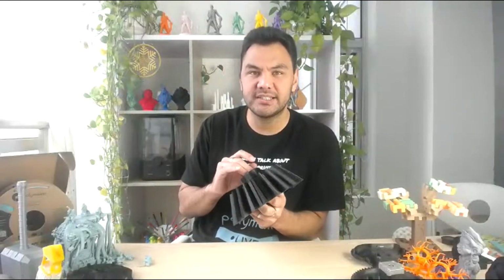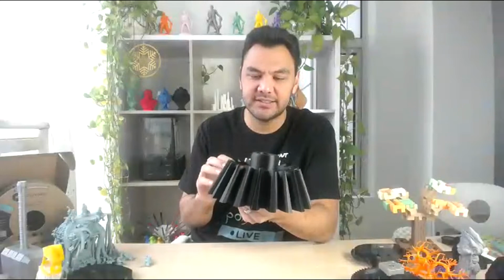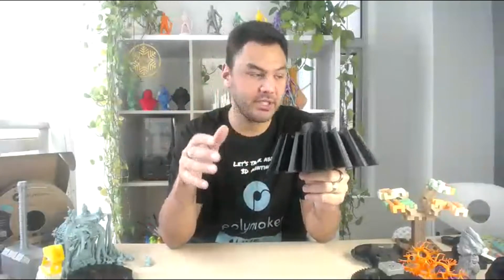The one we have is called CoPa, so it's a blend between 6 and 6.6. I don't know the exact difference in terms of molecular composition, but what this copolyamide 666 brings is the printability compared to our PA6. So it reduces the printing temperature. You can print our CoPa at 250, 260, but the PA6 has to be printed at 280 to 300.